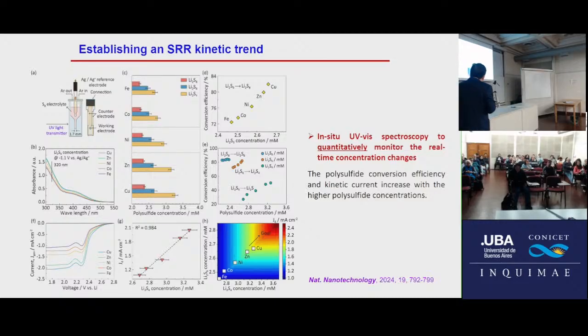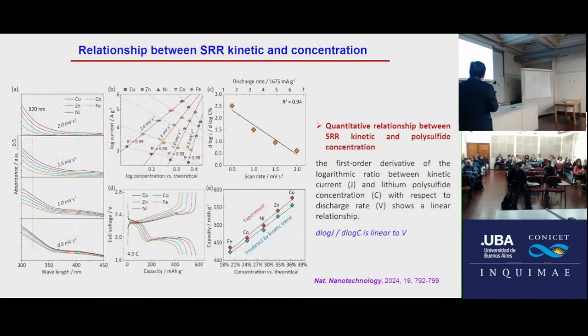It means if we want to achieve higher kinetic current density, we must consider increasing polysulfide concentration. After that, we use the same method to measure the concentration of the polysulfide at different scan rates. Actually, this scan rate also indicates different charge rates. You can see this is a linear relationship, right? So finally, we can establish this one, log J versus log C. J is current density, log C is polysulfide concentration, and this relationship holds with the scan rate, which is the charge rate.